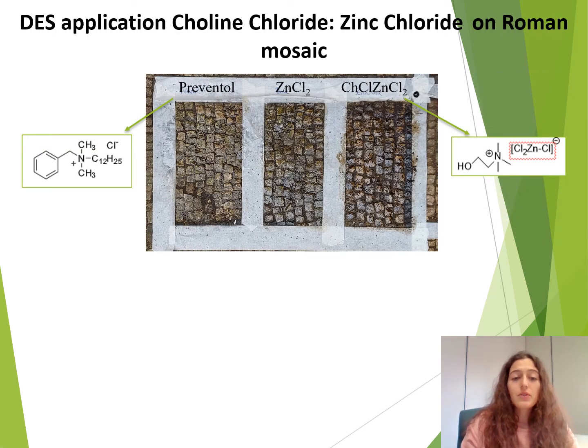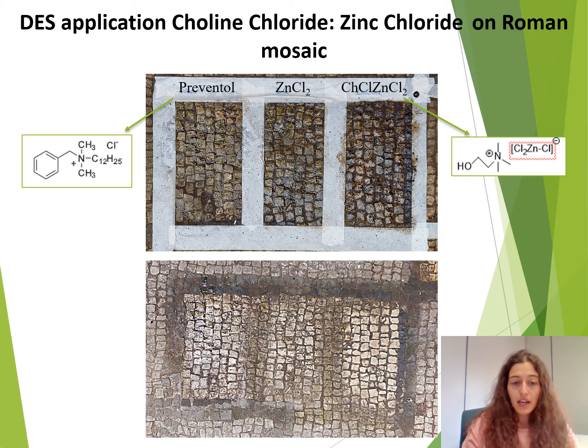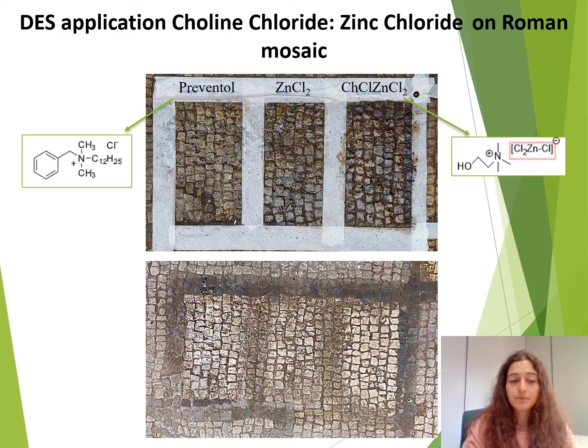Choline chloride zinc chloride was applied on a Roman mosaic. In this image, we can see the application of choline chloride zinc chloride in comparison with a saturated solution of zinc chloride and Preventol. After the application, choline chloride zinc chloride showed a good cleaning effect.